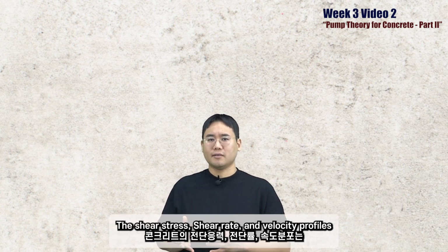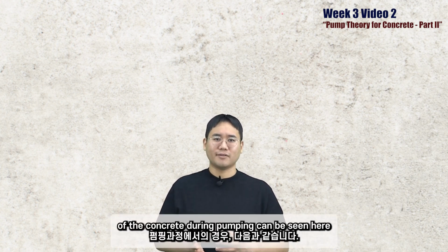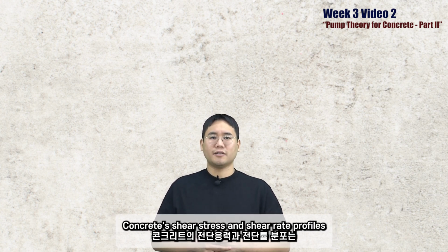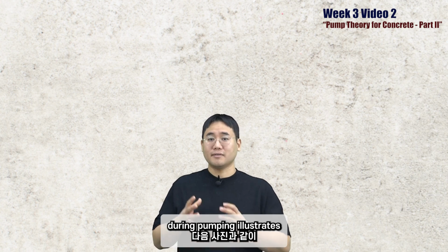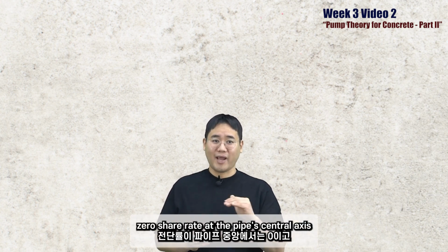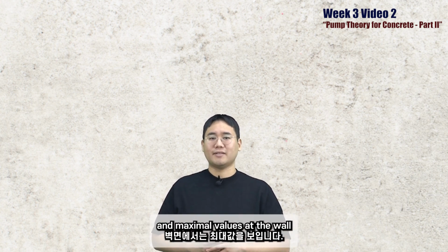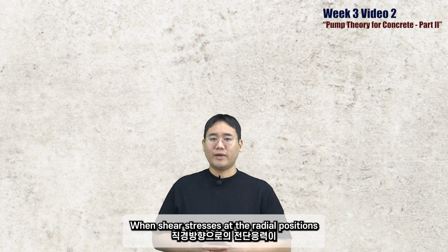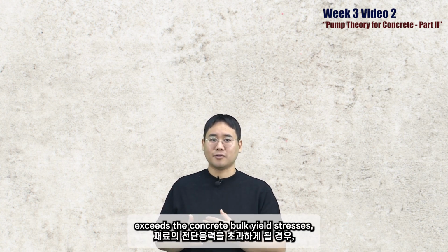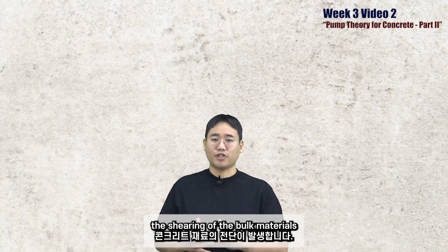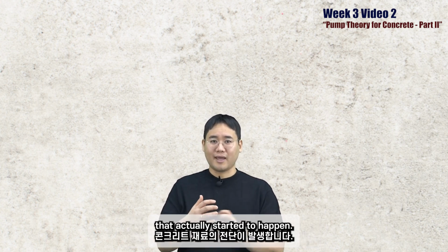The shear stress, shear rates, and velocity profiles of the concrete during pumping can be seen here. Concrete's shear stress and shear rate profiles during pumping illustrate the zero shear rate at the pipe central axis and maximal values at the wall. When shear stresses at the radial positions exceed the concrete bulk yield stress, the shearing of the bulk material starts to happen.